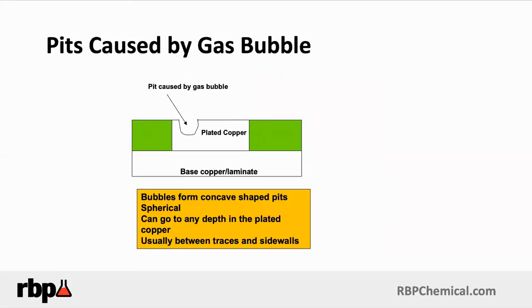When pitting is caused by an air bubble or gas bubble, it may or may not go all the way down to the base metal. Typically, an air bubble or gas bubble pit is near the edge of where the photoresist and the plating meet, and they are typically very uniform in shape — concave and spherical — most likely very close to the trace where the photoresist sidewall meets the plated copper. These voids are generated where bubbles come from poor filtration, or pump cavitation in the plating solution causes the pumps to introduce finely dispersed air bubbles that get trapped onto the sidewalls, creating pits.